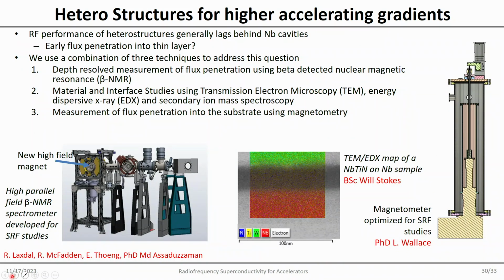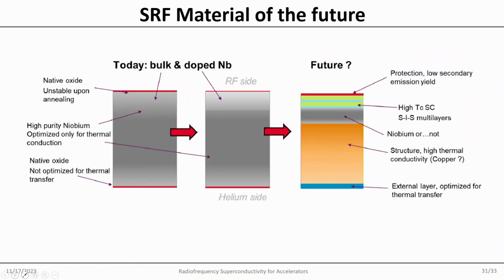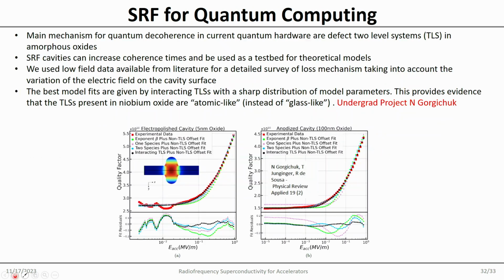So the combination of these 3 should give us insight into how we can go from the current way we do SRF right now, niobium, to a multilayered structure. This is how a perfect SRF cavity material would look: you have these multilayers for high field. Also, niobium is not a perfect thermal conductor. It would be good if everything could be on copper, and then you would even optimize both sides: one for perfect heat contact, and the other to avoid field emission and so on. So this is how an ideal SRF cavity in the future could look.